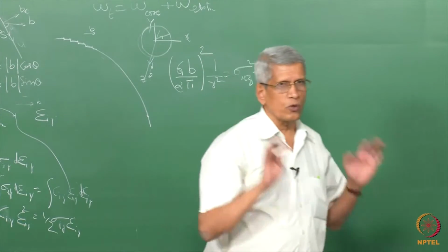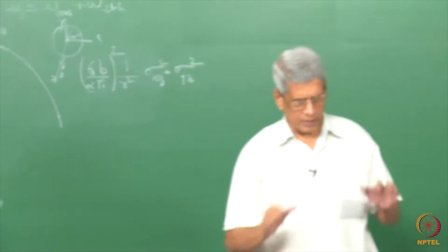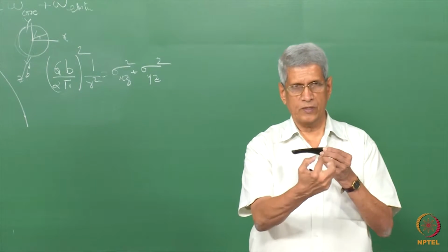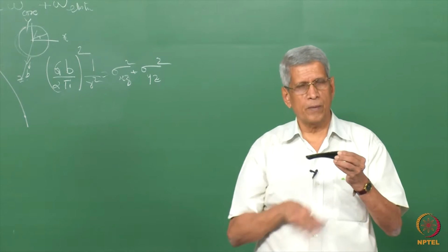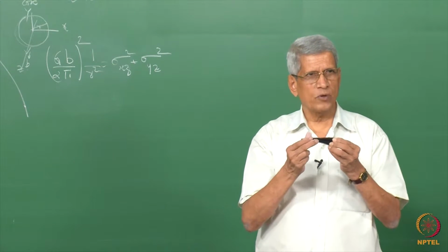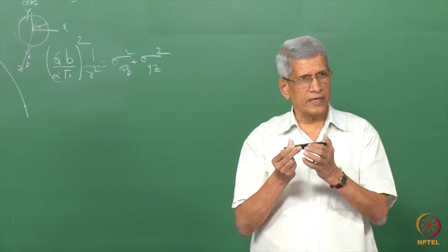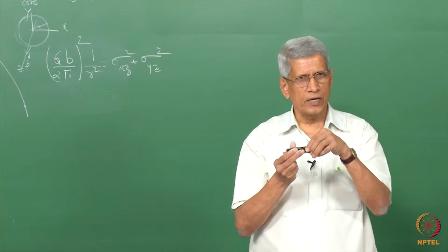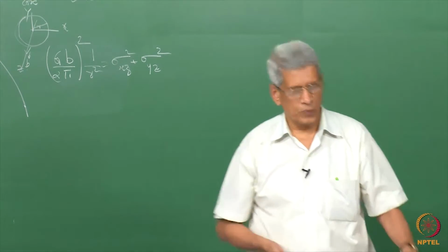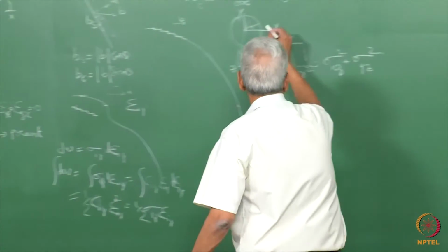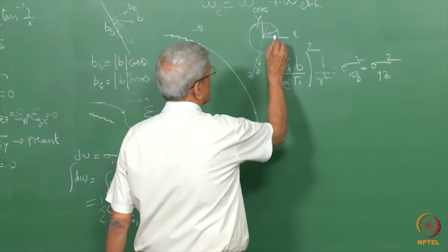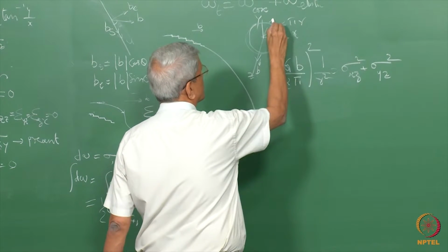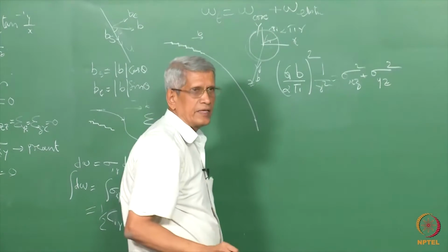Suppose we wanted to know the total strain energy. We know that the displacement is taking place. Suppose we take a material like this, with a dislocation line present like this. Throughout the sample displacement is there. Now we have to calculate the strain energy at every point on that sample and add them together, then only we get the total energy. In this case we can take a circumference of 2 pi r into a small distance dr. This is the increase in area.